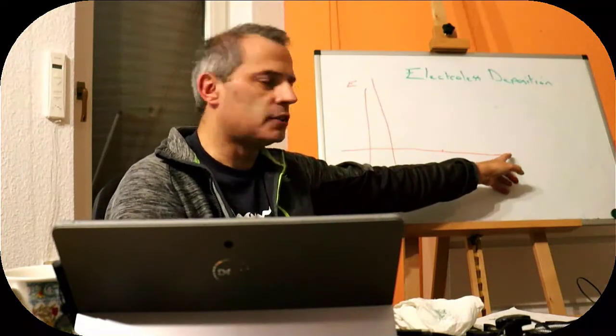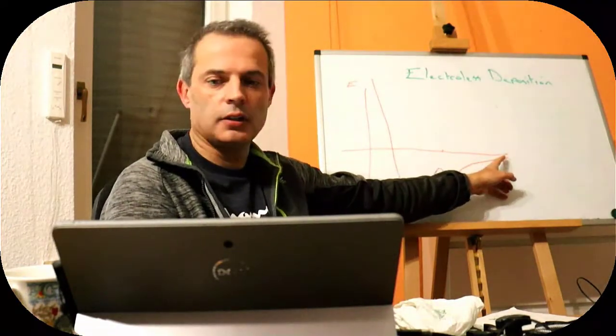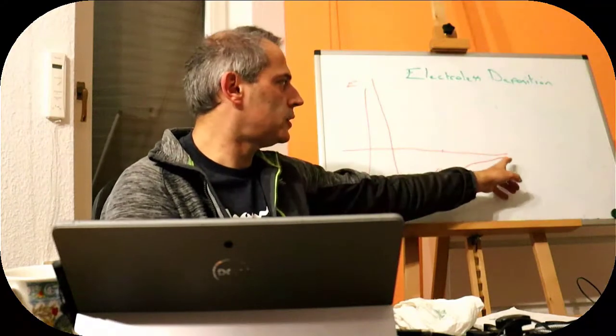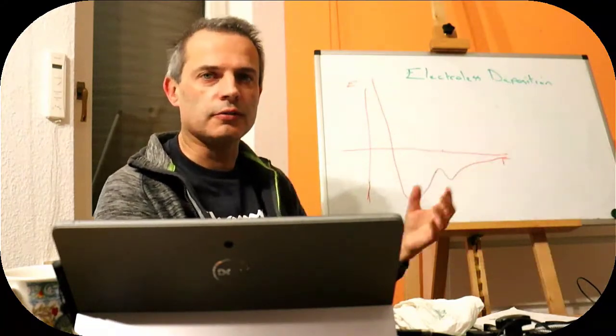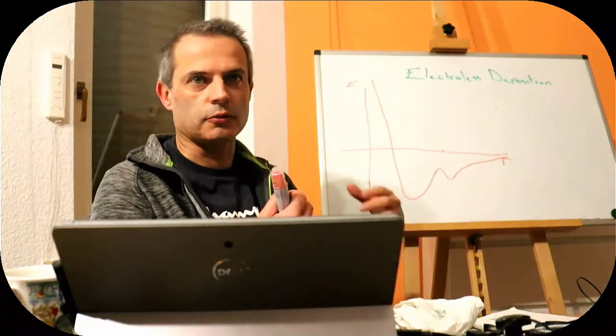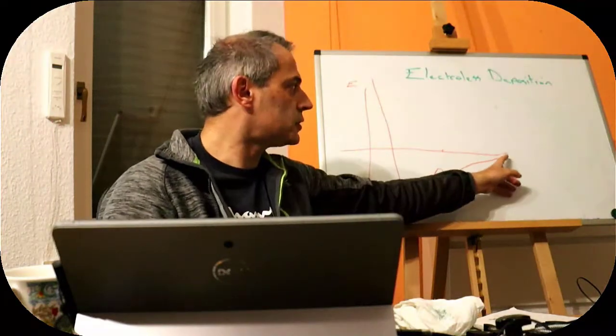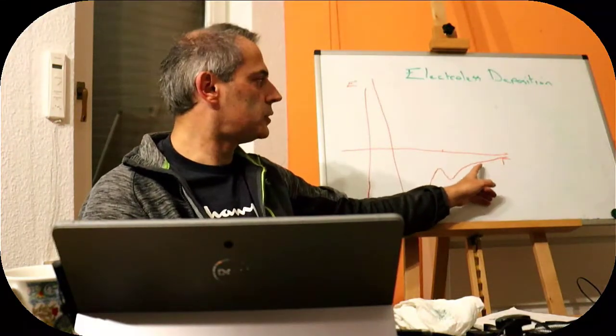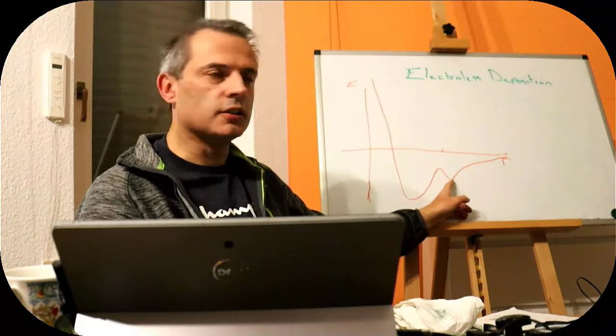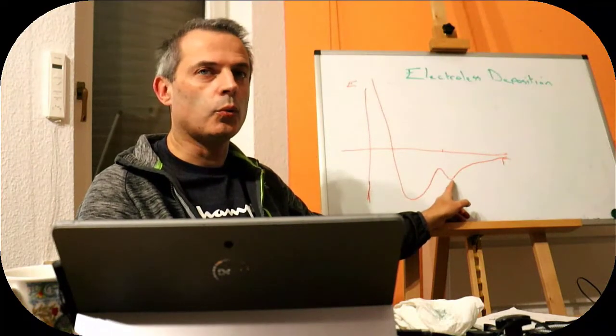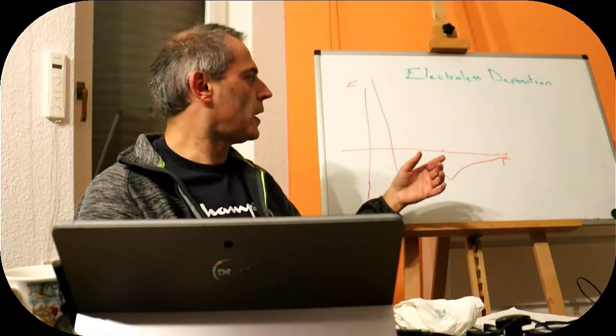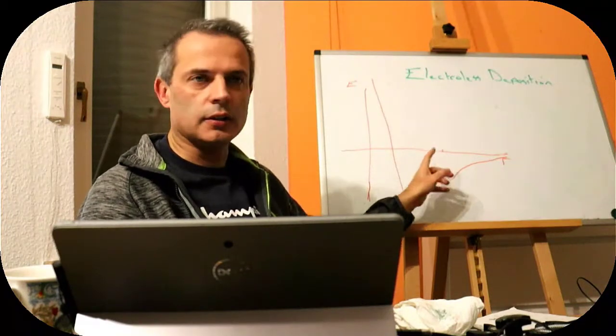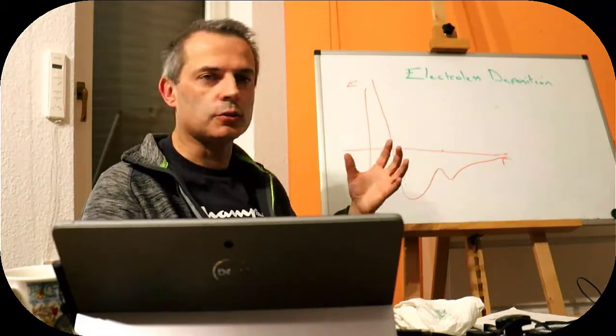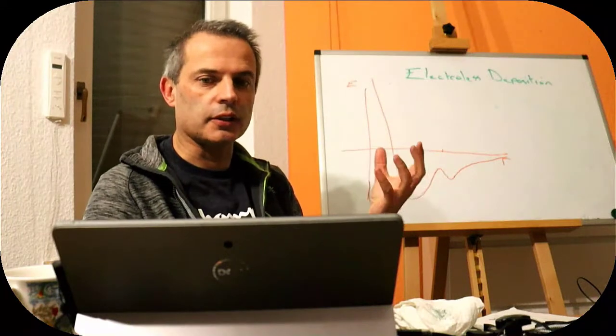As we can see, it's attracted to the surface out here at far distances, but not very much, because obviously the further a charge is away from a surface or another charge, the less the interaction. As we bring it closer, we get down and down and down, and we get to this secondary minimum where there's water in the way, and on its own it can't beat this energy barrier, which would be squeezing the water molecules out of the gap in between.